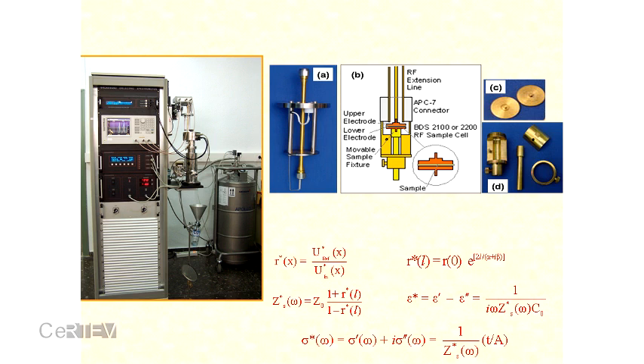Here we use transmission line measurement. You can have the so-called gold electrodes. These samples are here, and some microwaves are entering or falling on the sample surface, and they get reflected. So by analyzing the phase angle and amplitude of these reflected waves, we can determine the capacitance and conductance, or finally the impedance, and from this impedance we can get the real part and imaginary part of the conductivity. And it is a very tricky problem. So up to that we can have a frequency range of up to gigahertz. This is the experimental setup which we are using in our laboratory in Kolkata.